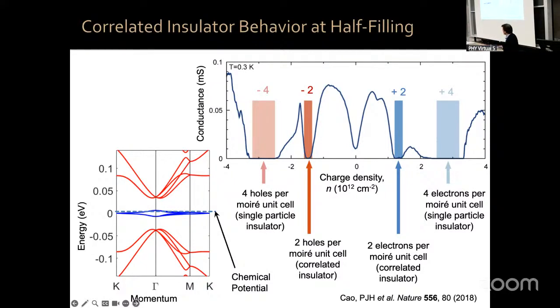But what happened with my students—I don't have the temperature dependent data here, but let me tell you what happened—this was measured at 300 millikelvin. Next to this insulating behavior, there was a peak in conductance. And this peak, if you increase the temperature, decreases. If you decrease temperature, it increases.